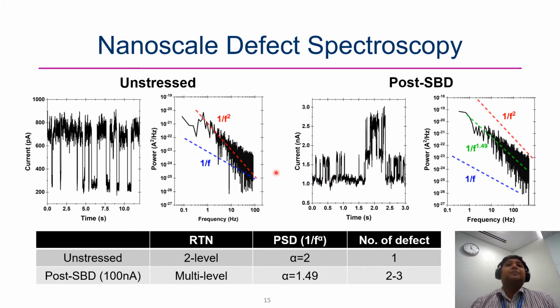And in terms of the power spectral density, one can see that for this two-level RTN, we have the simple slope of 2, 1 over f squared noise. However, as the number of defects grows, it changes close to 1 over f. So in this particular case, we have 1 over f to the 1.5, which is close to 2 defects modulating the charge transport.